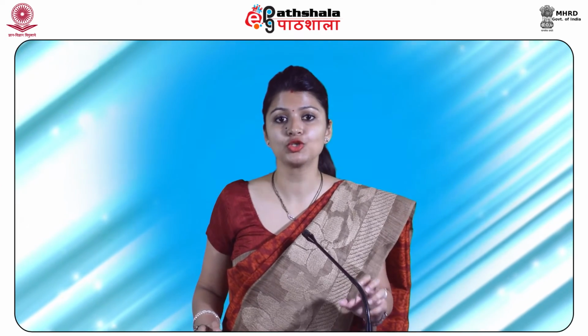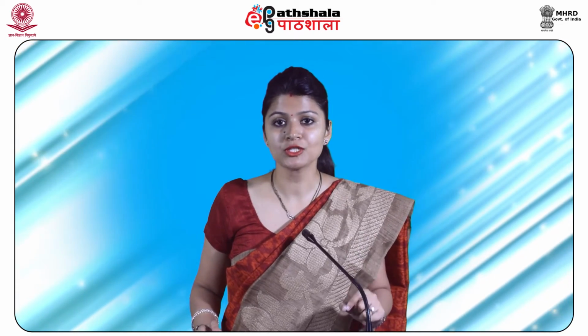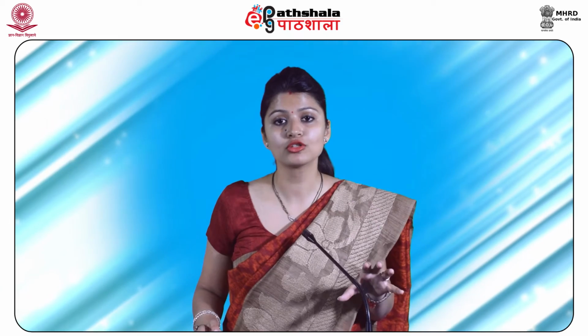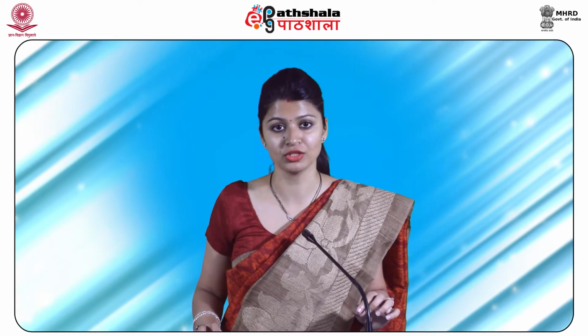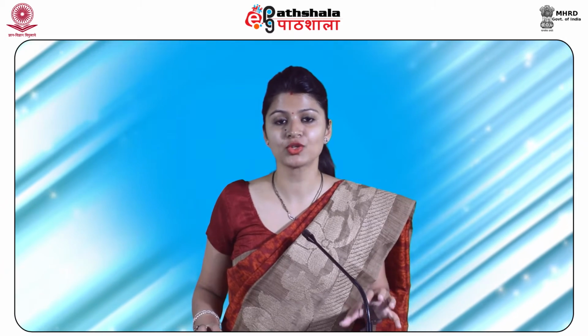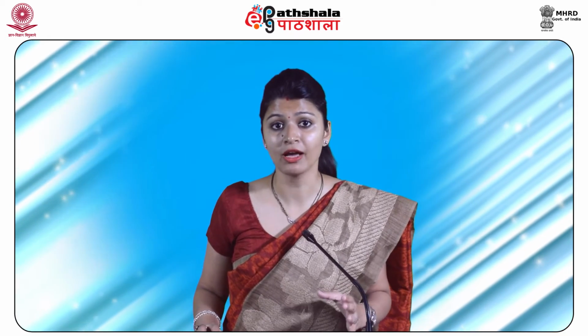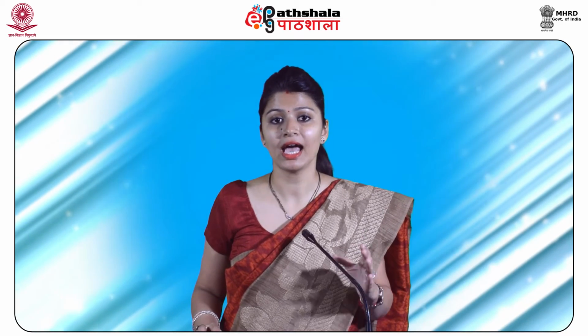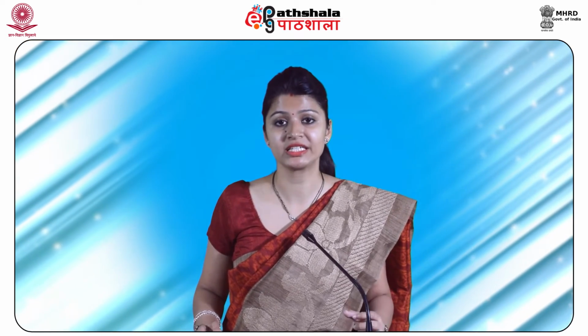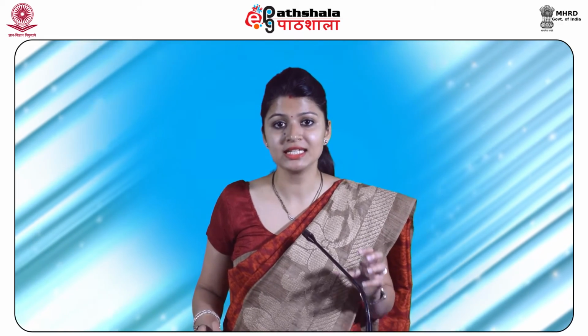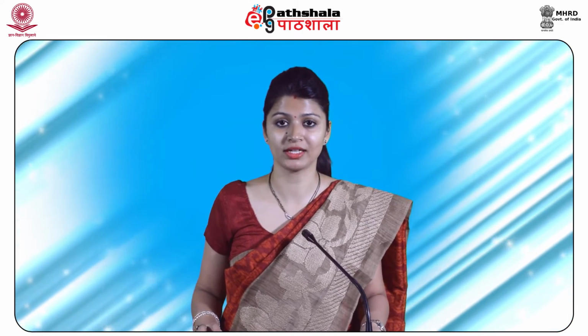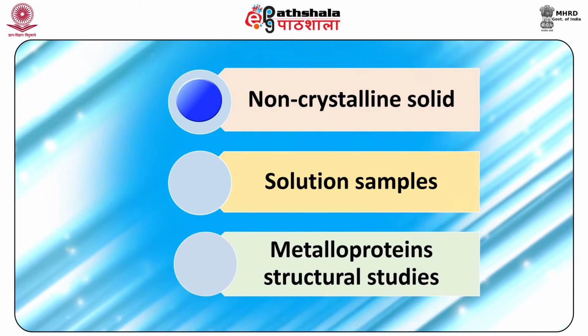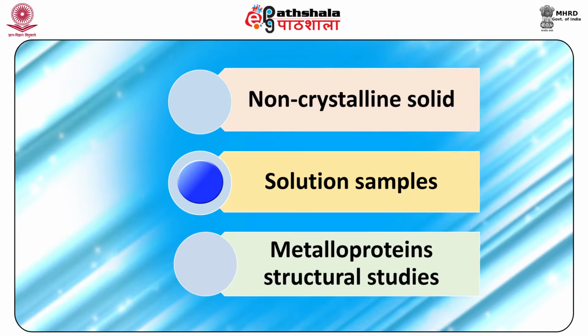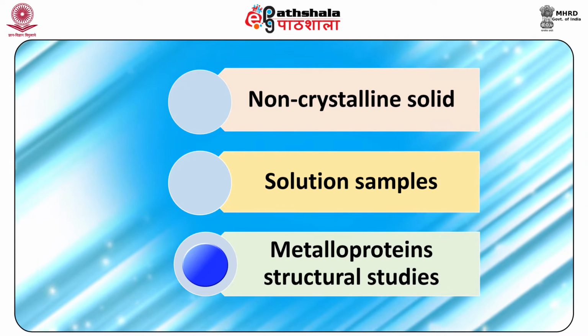By studying the energy of the X-ray absorption edge, where the onset of absorption occurs, one can often determine the oxidation state of the metal ion under consideration. Transitions from the inner shell to the valence shell of electrons also allow one to get electronic structural information in favorable cases. Modulation of the X-ray absorption energy spectrum by backscattering from neighboring atoms produces an extended X-ray absorption fine structure, abbreviated as EXAFS, from which details about metal coordination geometries can be extracted. The method has great utility in that non-crystalline solid and even solution samples can be studied, and it can be applied in metalloprotein structural studies.